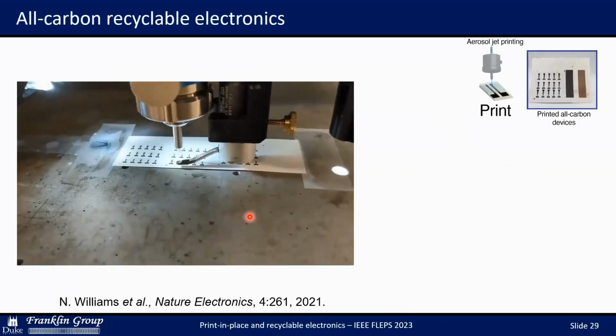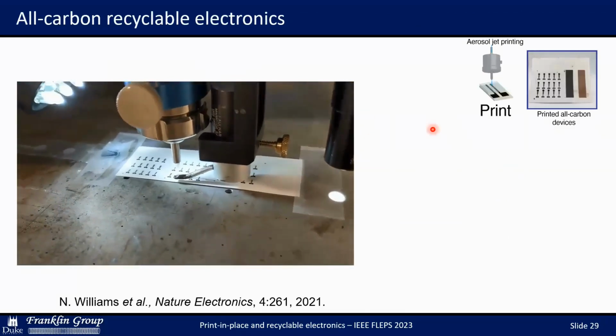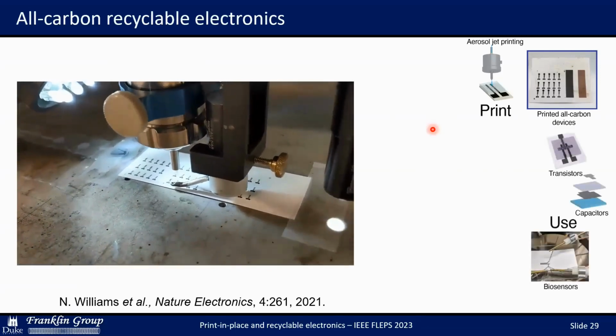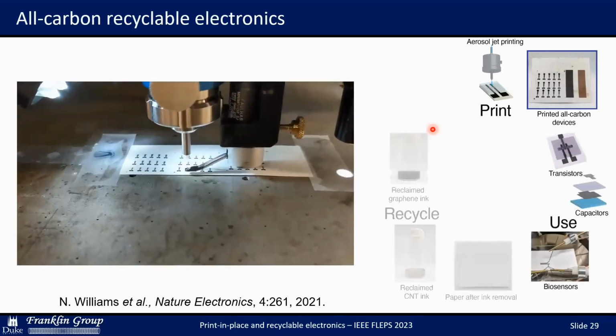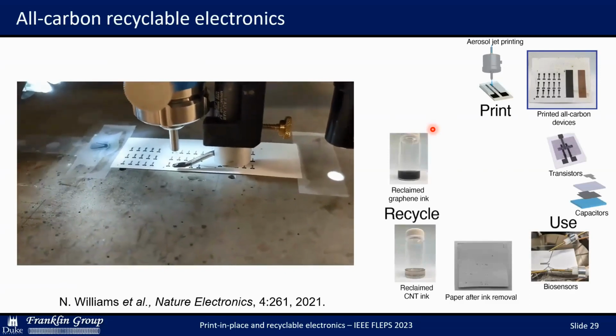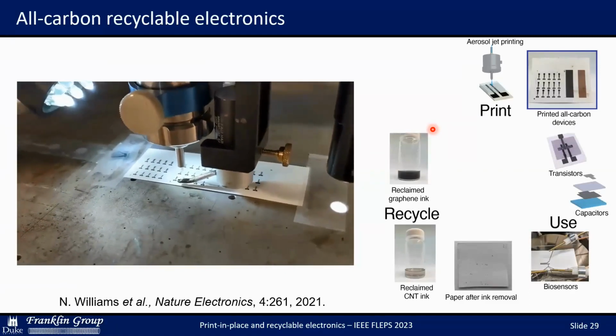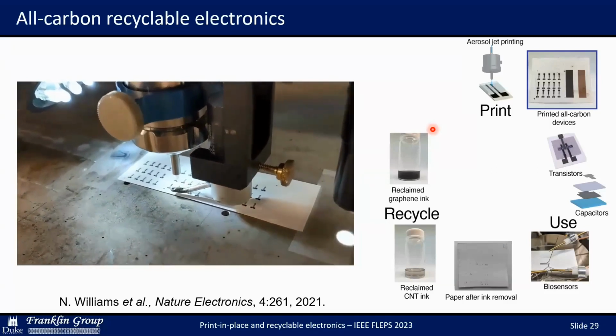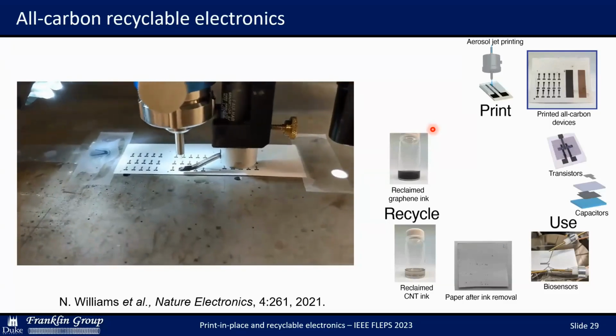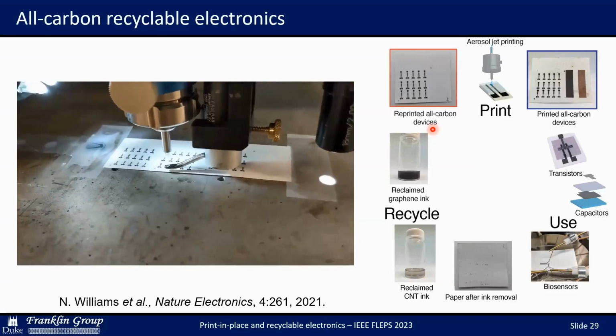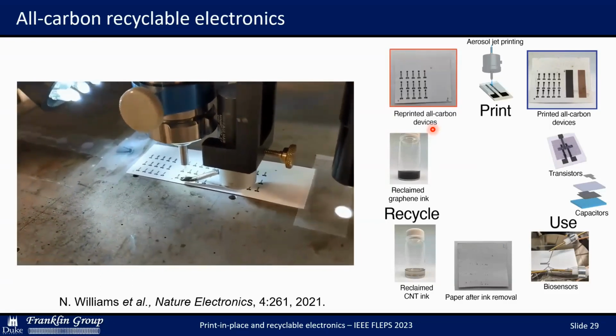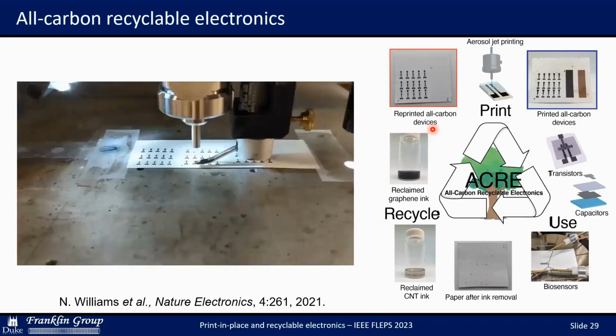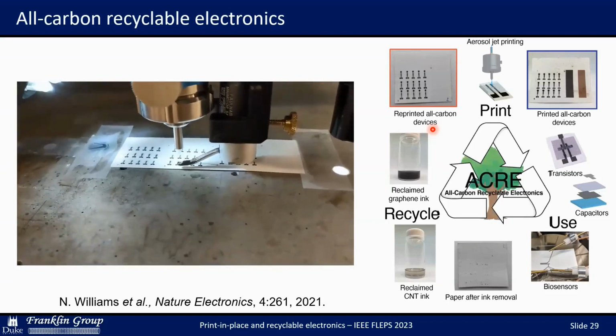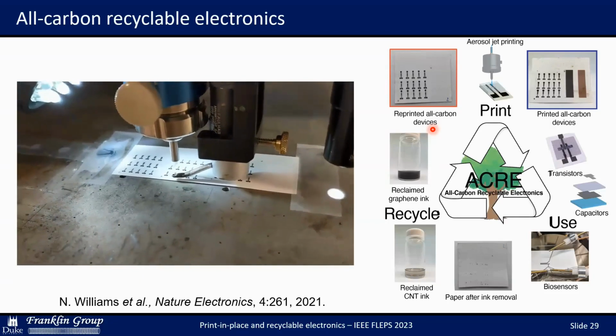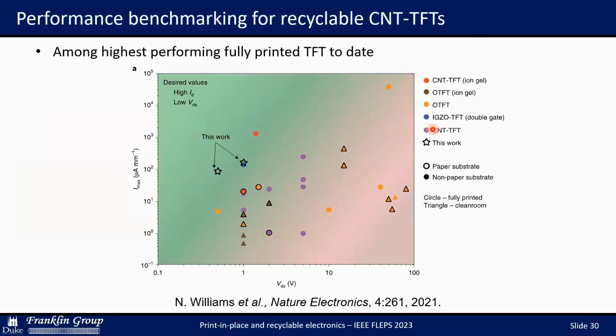And when you print them onto a paper substrate, you can see the aerosol jet printer running on the left, into transistors, biosensors, capacitors, and whatnot. We then showed that you can reclaim the ink that was printed onto the substrate, the nanotubes and the graphene, separate them into completely recycled inks, and reprint the same devices again. So there's actually a full life cycle that's capable of being achieved in the use of all of the electronic constituents in these devices. So this gives you a bit of a benchmark of the performance of those devices.